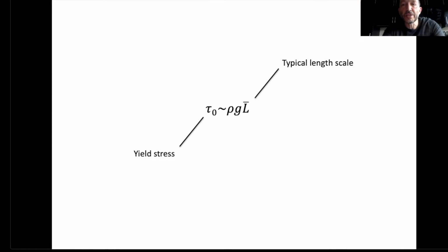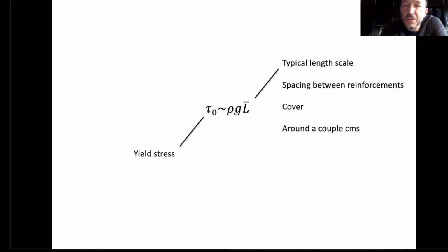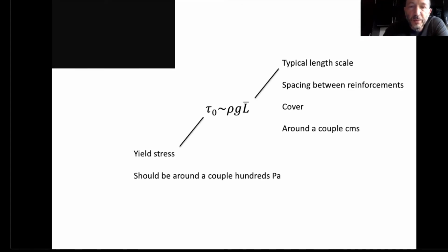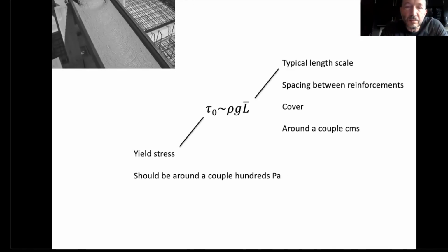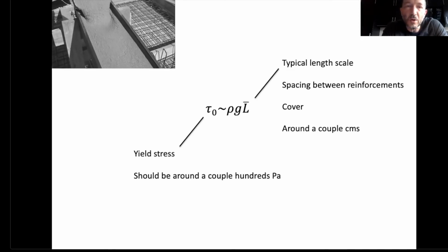Another consequence of this relation is the so-called self-compaction. So I'm coming back to this relation, yield stress on one side, typical length scale on the other side, and I try to imagine now the value of the yield stress below which I can fill all the molds, and I can fill all the delicate and narrow parts inside the molds, between the steel bars, for example. So what is the critical value below which I will be fine, and gravity will be sufficient to cast anything? This length scale is of the order of a couple centimeters, and it means that the yield stress for typical density concrete should be around a couple hundred Pascal. And this indeed is the yield stress of self-compacting concrete or self-compacting mortar.